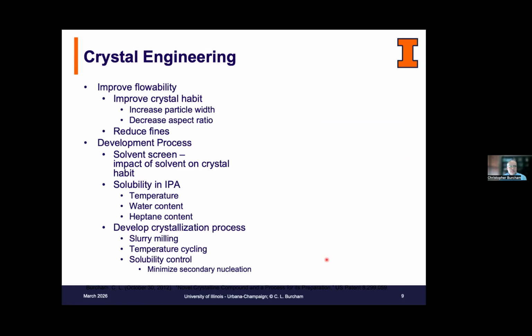This led to a very intense crystal engineering effort to improve flowability. We knew we needed to improve the crystal habit by increasing the particle width and decreasing the aspect ratio as a result. We knew we had to reduce the fines. And so we did this through an experimental process of solvent screening, looking at the impact that the solvent would have on the growth of the different faces of the crystal. We looked at the solubility once we chose our solvent as a function of other solvents that we saw had a beneficial impact on our morphology, as well as an anti-solvent, which would help us ensure that we could control crystal form below that enantiotropic temperature. And then we developed the crystallization process utilizing slurry milling, temperature cycling, and solubility control.